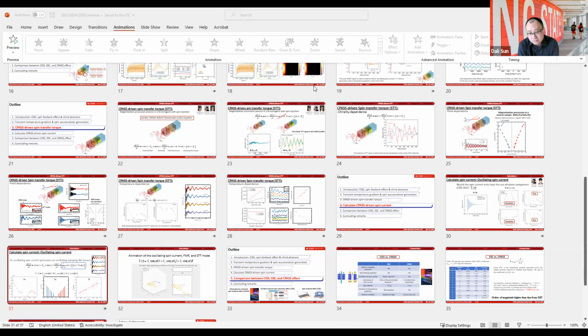So what's your second question again? Basically, from this perspective, can you think about an experiment where you probe antiferromagnetic interaction? Yeah. We did mix chirality. Because it's a chiral perovskite, we can mix cations with left-handed and right-handed chirality in the same molecular location. We did such an experiment. They call this material racemic chiral perovskite. Once they form the racemic material, there is both left-handed and right-handed chirality in the perovskite. It doesn't have any structural chirality. They just cancel each other, and we don't see such a signal.